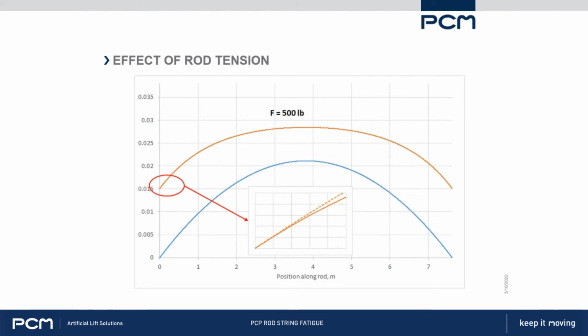Unless, of course, you've got big changes in wellbore curvature. But if you have a section of the well where the curvature is consistent, with several rods going through that, those couplings are going to be parallel to the wall, and they're going to stay that way. As we put tension on, the rod tries to take the shortest path between the couplings. So the more tension you put on it, the more it's likely to try and take that shortest path.